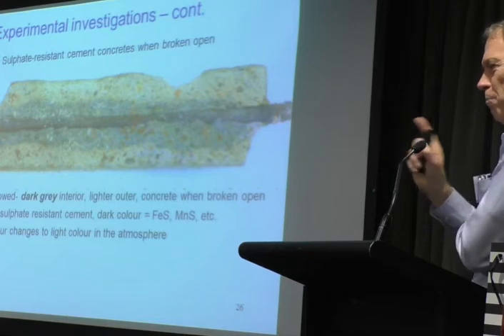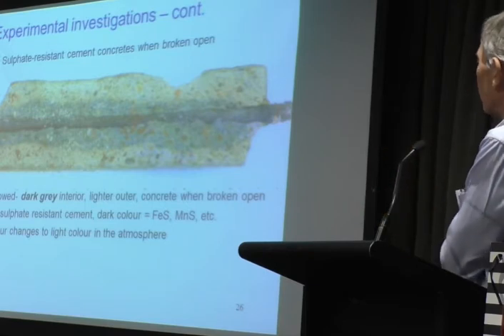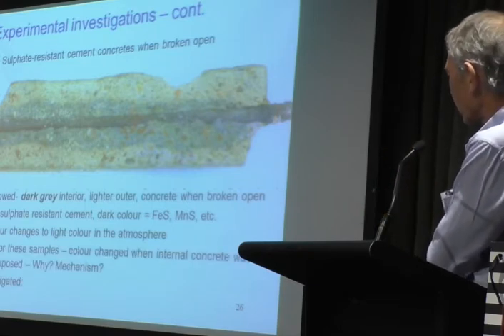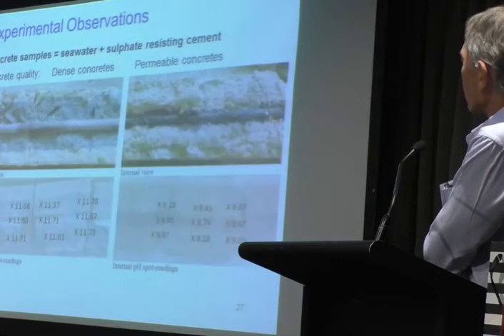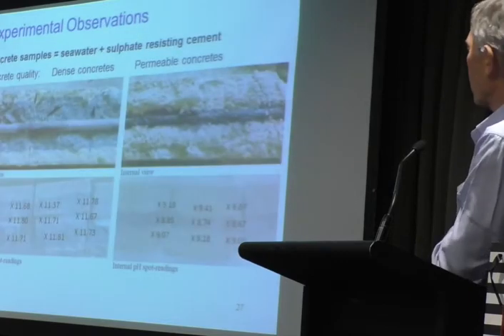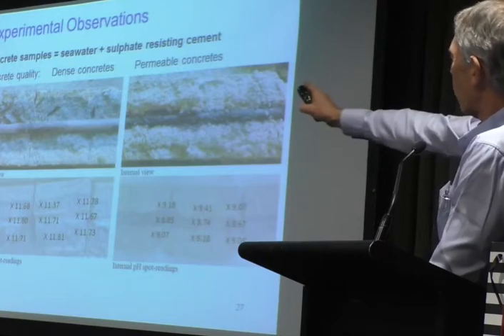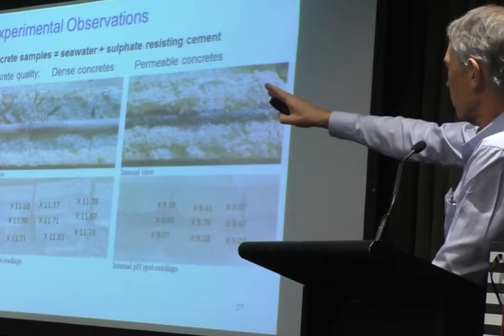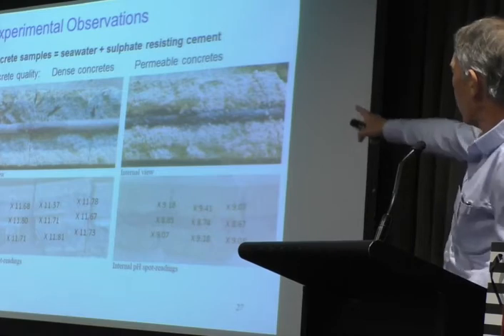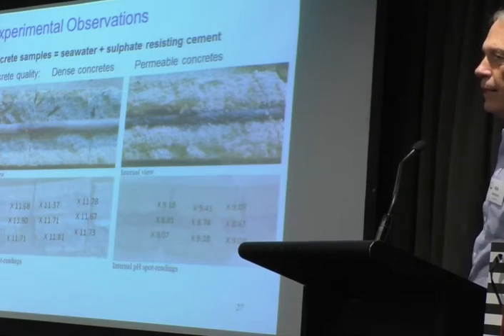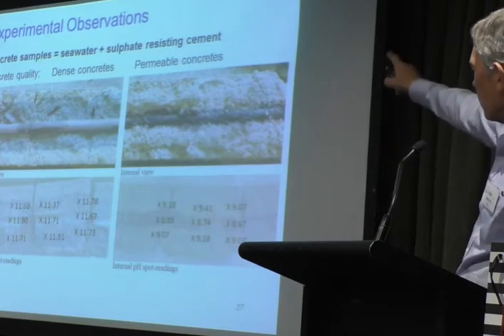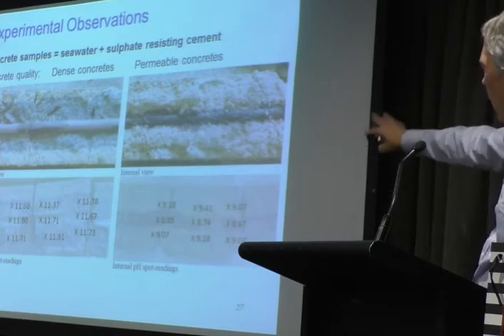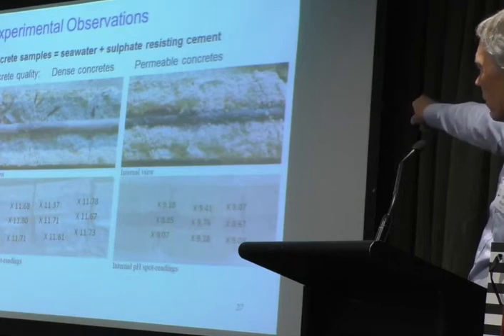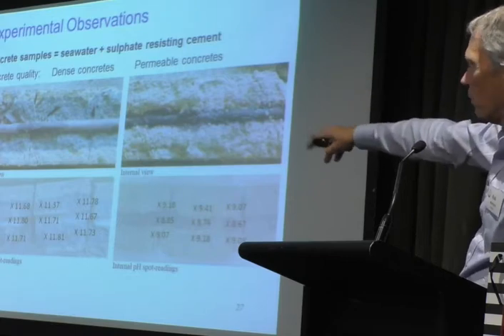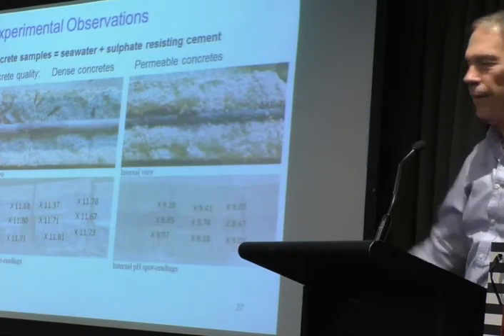Well, when I say they haven't been exposed to the atmosphere, that's actually not quite right, but we'll come to it. So what's going on? So we looked at that. So here's a nice comparison. Dense concretes on the left-hand side, the one similar to the one I just showed you. Really permeable concretes on the right-hand side. And you can see there's no dark grey material. We then went and looked at the pHs, and you'll see the one on the right-hand side got pH down to about 9 or so, and the bar is corroded. The one on the left, there's virtually no corrosion, the pH is still around 11, 12, something like that.